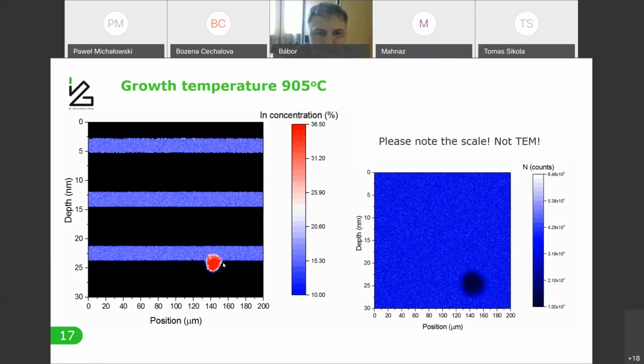I can't complain, because without the square stencils I wouldn't reach such a good depth resolution, because as I said, you really need a homogeneous beam. The actual lateral resolution, maybe it's not exactly 1 micron, maybe it's a little bit better, but definitely in this regime. So it's definitely not something like 50 or 100 nanometers.